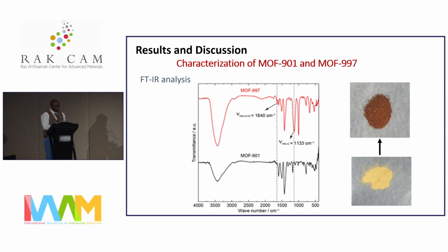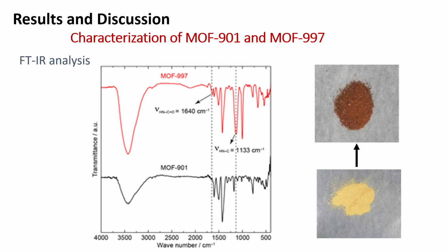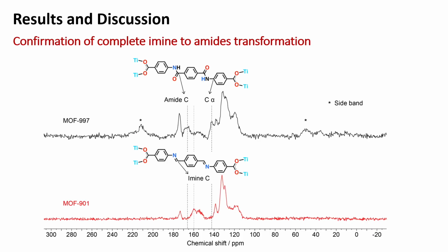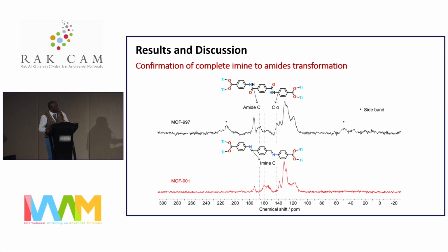As you can see clearly, we have a shift in the peak region for the imines at 1626 to about 1640, which shows a shift from imine to amide. And then for us to know whether this is complete oxidation and conversion, we had to do solid state NMR. As you can see, we were able to completely shift the structure of the imine from the region of 160 parts per million to the region of the amide. And also we were able to see the carbonyl-carbon formation and complete disappearance of the characteristic imine bonds.